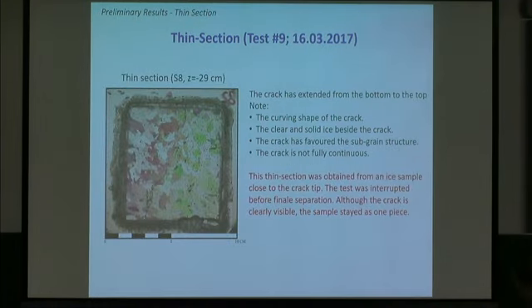And again, at this depth of minus 20, or at 29 centimeters from the top down, you can see in this thin section clearly the crack running over here. And also you can see that it diverts a little bit, goes around, clearly seeking for weakness in the ice. This is very close to the crack tip, so the crack tip is up somewhere here. And we also see that it's not fully continuous the way we see it on this slide taken here.